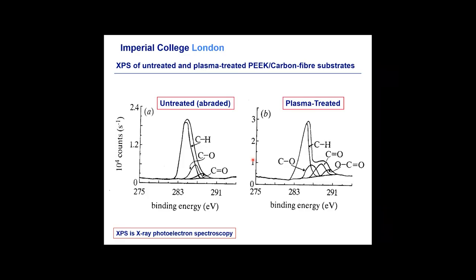Now we can look at this in more detail as surface chemists using a technique called X-ray photoelectron spectroscopy. In this technique, we fire X-rays at the surface and look at the photoelectrons which are ejected. The photoelectrons just come from the first few nanometers of the surface, and they identify the groups on the surface regions of the material. So here's the untreated, just lightly abraded material, and here are the polar groups. There are some, but not very many, and hence it has a low surface energy, as you'll see in a minute.